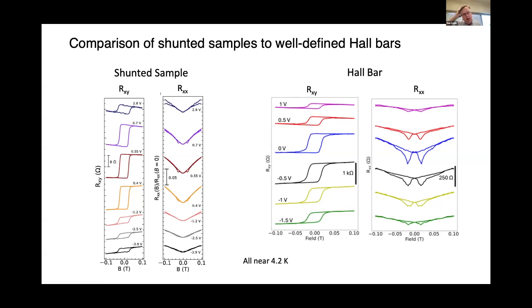What's new once you take exactly the same structures and etch them into Hall bars is you get about a factor of 50 increase in the Hall resistance just from eliminating all the shunting from the parts of the topological insulator that aren't in contact with the magnet. So now, once we have a well-defined Hall bar, we see the same phenomenology, but with much larger signals, both in the Hall resistance and in these butterfly patterns for the longitudinal resistance that have been ascribed to conductivity along topological edge states.